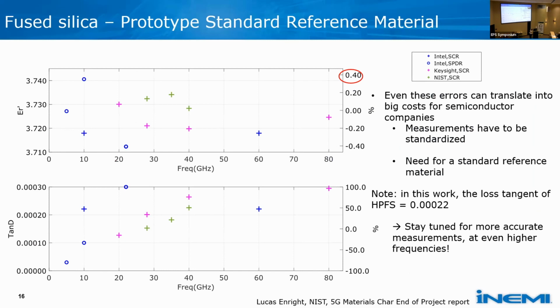This is data from that first project, where you're looking at the dielectric constant and loss tangent of a piece of high purity fused silica. What they did was send the same pieces on a round robin to be tested at a variety of labs. In this case, they used the thickness that was measured by one of the companies rather than each company also measuring the thickness of the sample. When they do these split ring resonator measurements, you need to know your dimensions very, very accurately. So there's a lot of ways to not be exact. Here we are with the same substrates being measured with a 0.4% variation across different companies across that frequency range.